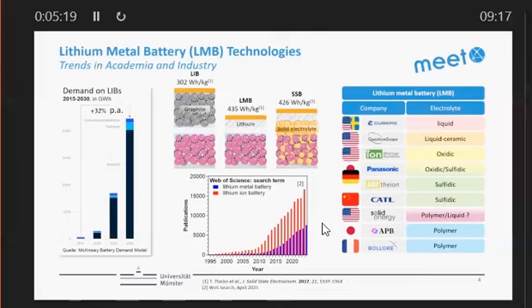So it's a big topic and it's increasing over the years, and we also have a lot of activity in industry with lithium metal batteries, some of them with so-called anode-free configuration. That means there is no lithium metal on the anode after assembly, but during the first charge it's deposited, coming from the cathode. And some liquid electrolytes, some polymer, and some sulfidic. So we have everything both in academia and in industry. So it's really a big topic.